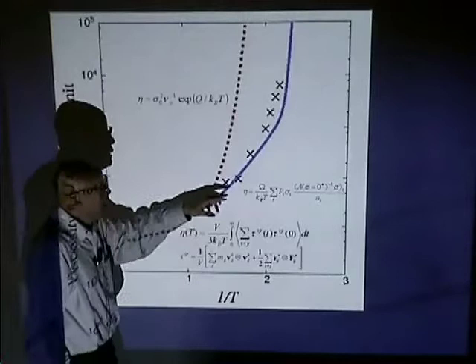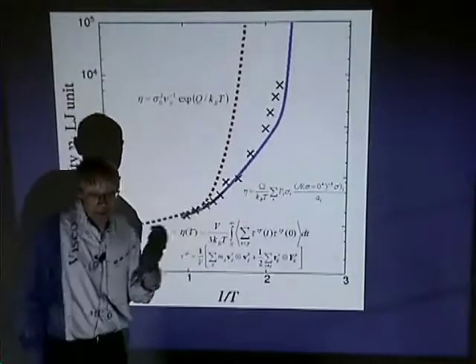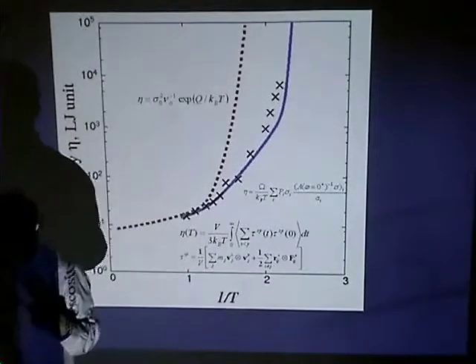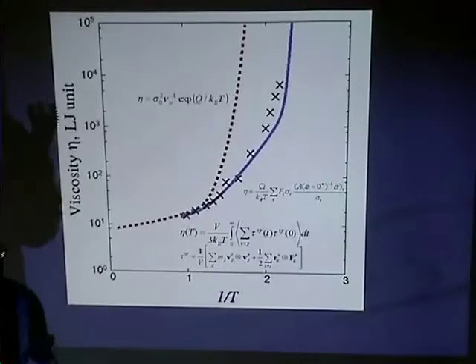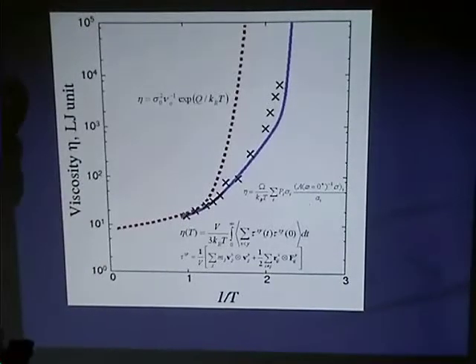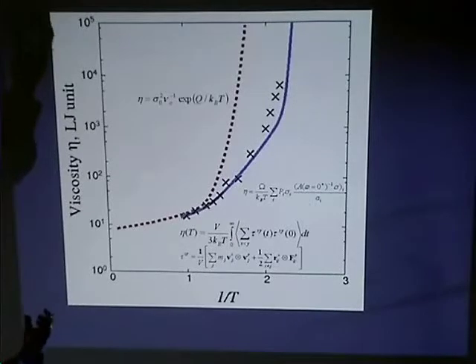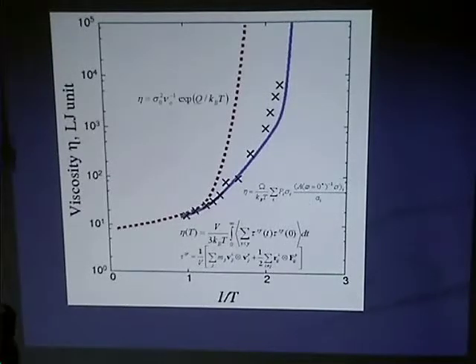Instead of using molecular dynamics to calculate the stress autocorrelation function, you can postulate a network model where you calculate the stress relaxation using activated kinetics. The activated kinetics comes from our transition state pathway sampling, using the same data.